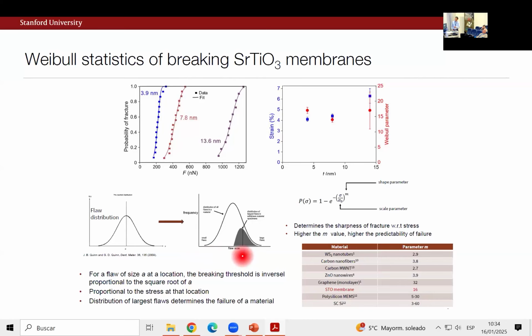So yeah, let me skip the details and just say that these fitted lines follow so-called Weibull statistics, right? There's basically just two parameters that are relevant. One is the overall scale parameter, but the so-called m shape parameter is very interesting because it's essentially the sharpness of this. So if I take this 3 or 4 nanometer thick membrane, what this is saying is that somehow statistically, almost all my membranes break at the same force, right?